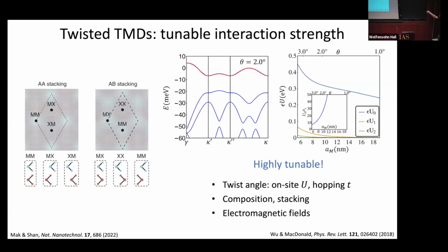But again, when you have a Moiré superlattice, this is just an example band structure calculation for a twist angle of 2 degrees, you can get very, very flat electronic bands, just like in the magic angle graphene case. But in some sense, these transition metal dichalcogenide systems are actually much, much nicer than the graphene-based systems, because in the transition metal dichalcogenides, you don't have a specific single magic angle where the bands become flat. So actually, the bands are flat over quite a broad range of twist angles. We heard talks in molybdenum ditelluride up to 3 or 4 degrees, similarly for tungsten diselenide. But these bands remain flat, really over a range of angles. So when you make these experimental samples and they relax and you're upset, actually it's not so bad. You don't have to hit that 1.1 degree just right. But on the other hand,